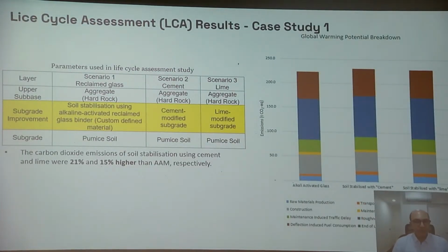After confirming the mechanical performance of the stabilized soil, we also conducted a comparative analysis of life cycle assessment for the alkali activated soil versus the soil stabilized by lime and cement. And the result shows that the alkali activated glass binder produced 21% less carbon dioxide than cement and 15% less than lime. So this demonstrates the potential of this binder as a sustainable alternative for soil stabilization projects.